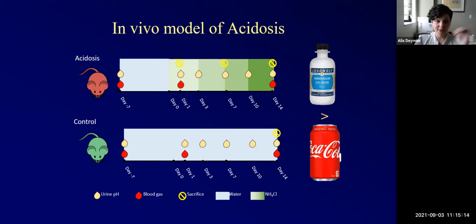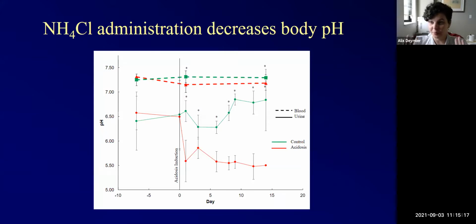So what happens when I do this? Here are the results from the pH from the blood and the urine. So here's pH as a function of time. And then the dotted lines up here are blood. So green is control. You can see, okay, pH didn't really change. But in the red, you can see that in my acidosis group, once I induce acidosis with this line, I have a drop in blood pH 1 day after they start to drink low doses of soda. After 14 days, we've actually maintained that low blood pH. In the urine, same thing. It immediately drops off after we add the ammonium chloride, and it stays low. So we've successfully induced acidosis in all of these mice.